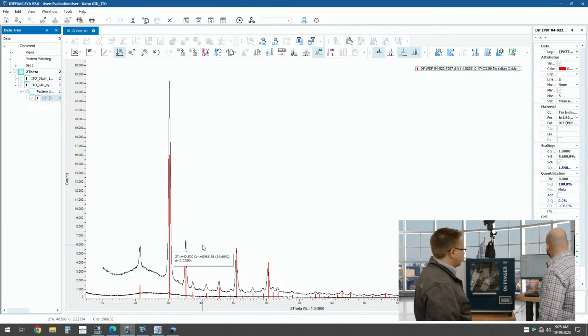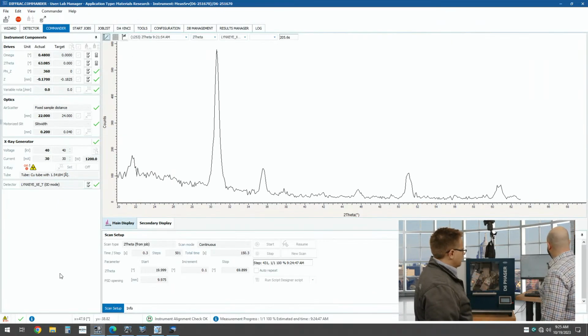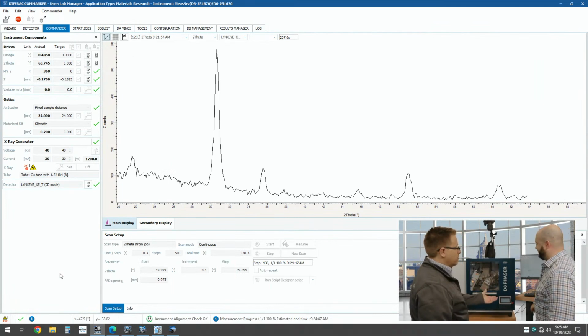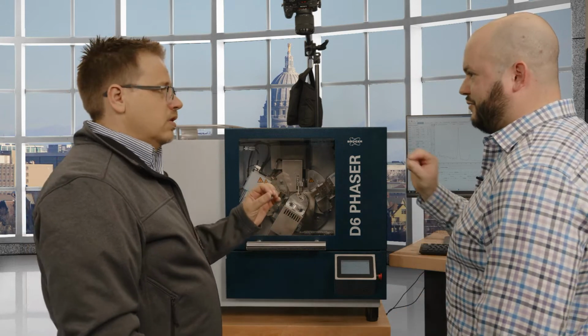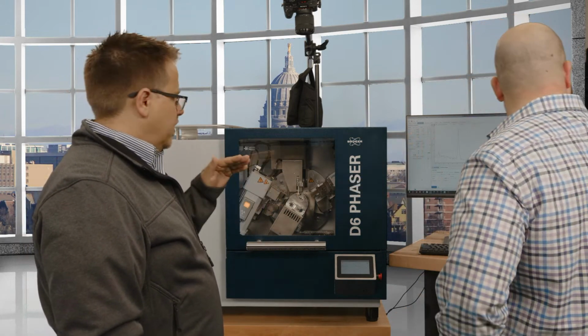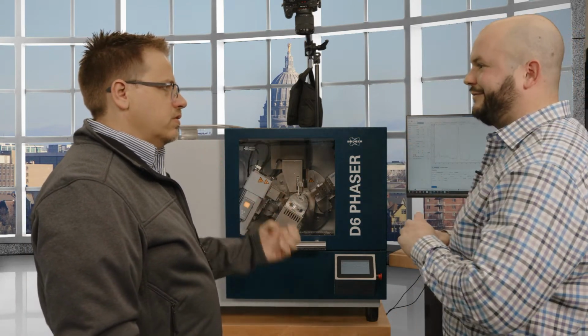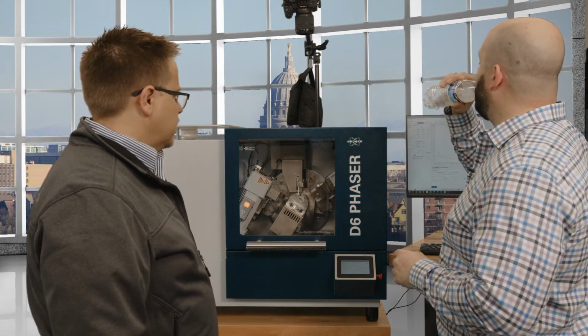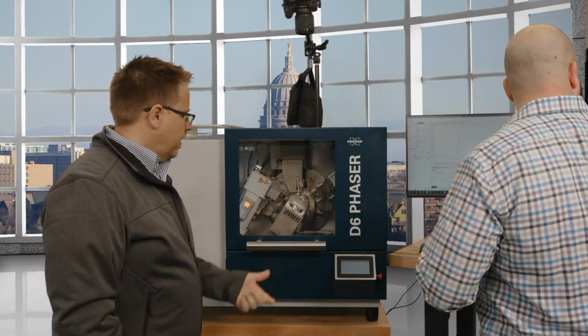Wow. Okay, so that's simple. And that's it. And there you go. And like we had measured before, it's actually a 25 nanometer film, and we're getting information from 25 nanometers. It's unbelievable. Yeah, and by keeping that incident angle low, we're able to get additional information from the top. So GID, XRR for films, good to go. Yep.